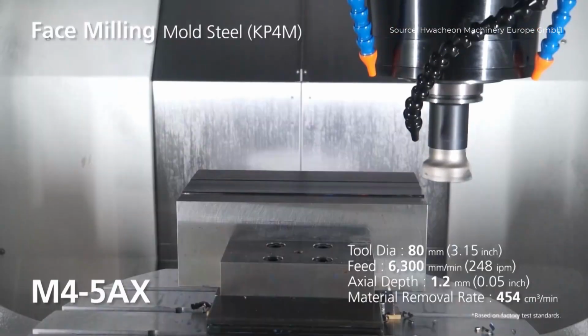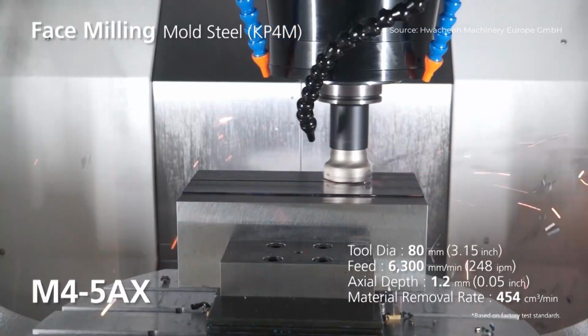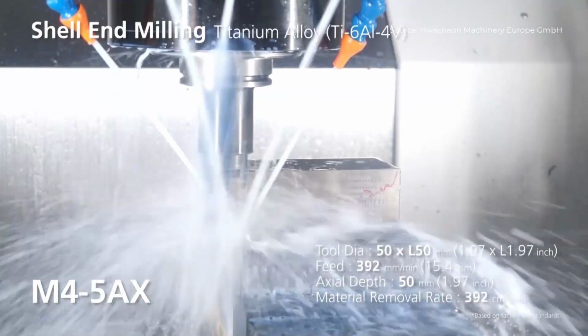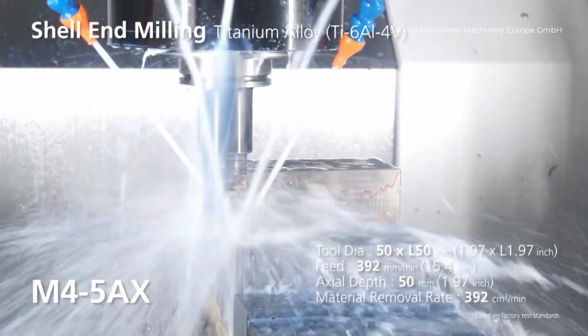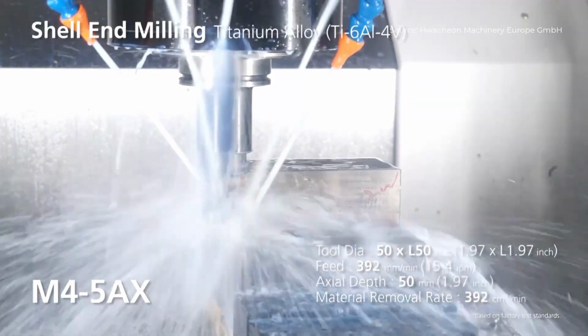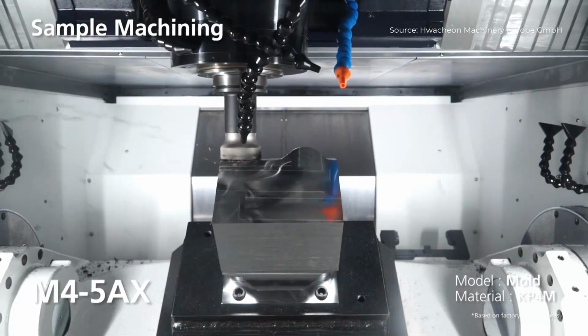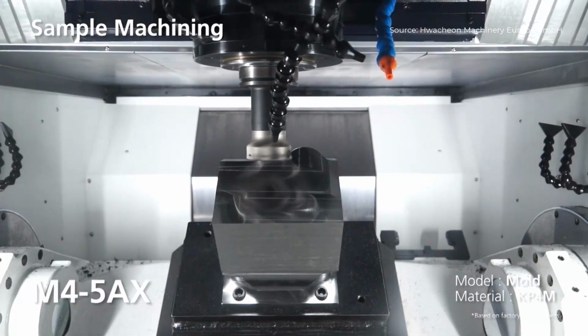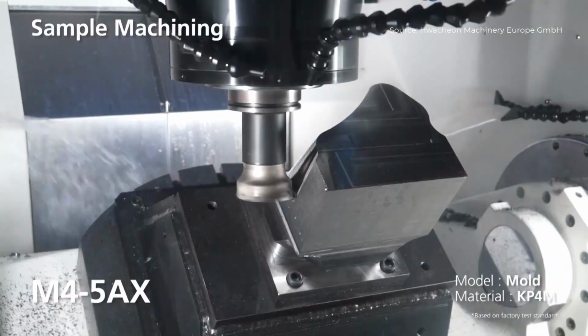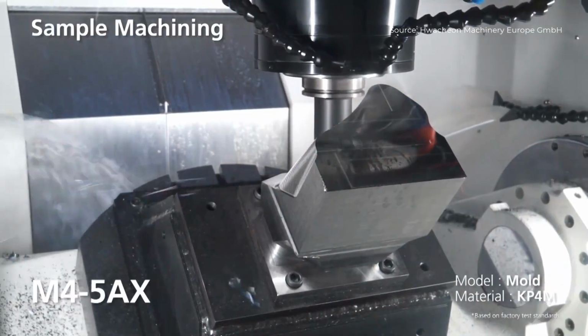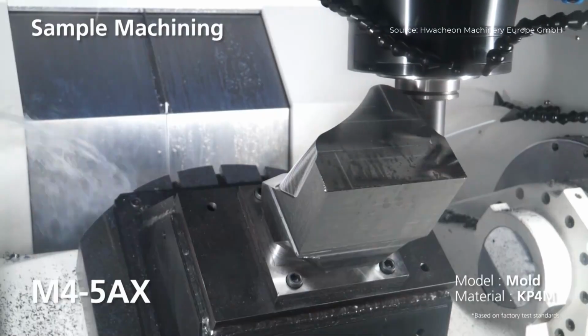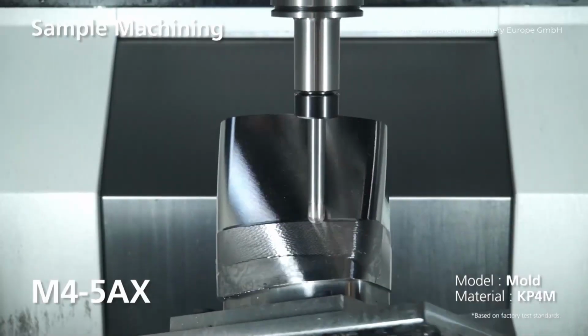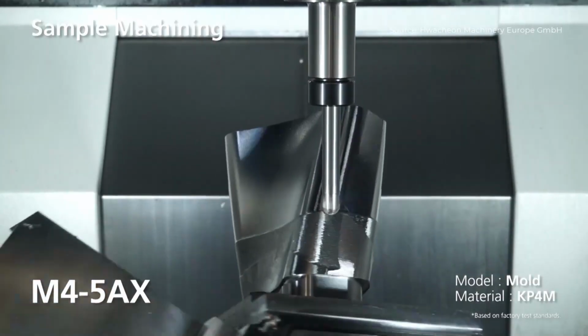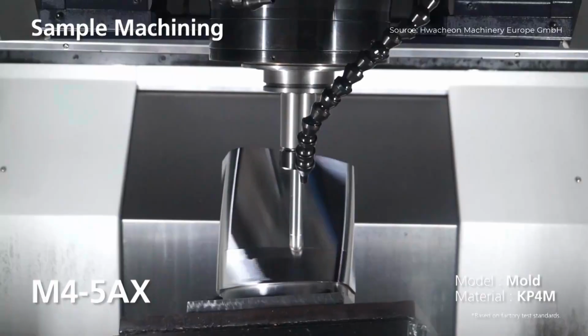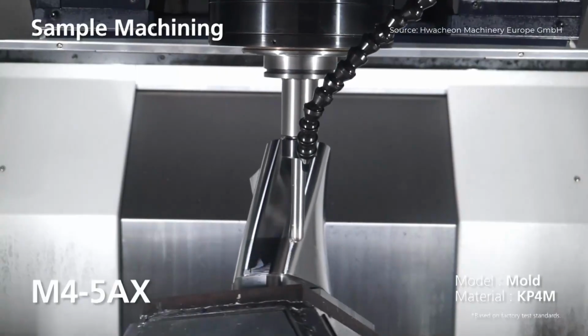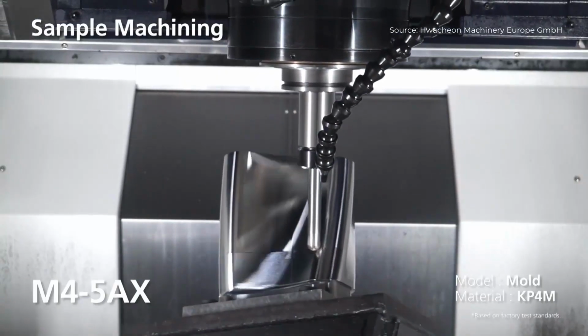The M4-5AX, with its high-torque spindle up to 1,009 Nm, excels in difficult material machining. It performs face milling of Mold Steel (KP4M) with a 80 mm cutter at 6,300 mm per minute feed and 1.2 mm depth, achieving a 454 cc per minute removal rate at 95% spindle load. The machine also handles tapping of carbon steel and shell end milling of alloy, supported by a twin drive Y-axis, scale feedback on all axes, and a cooling system that minimizes thermal distortion during continuous heavy-duty cutting.